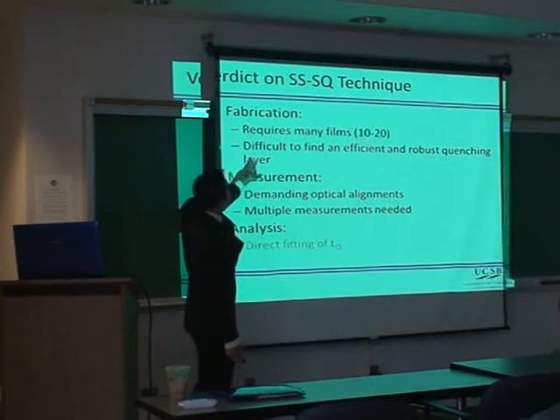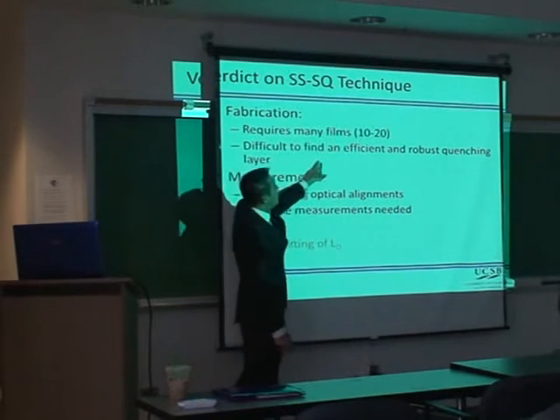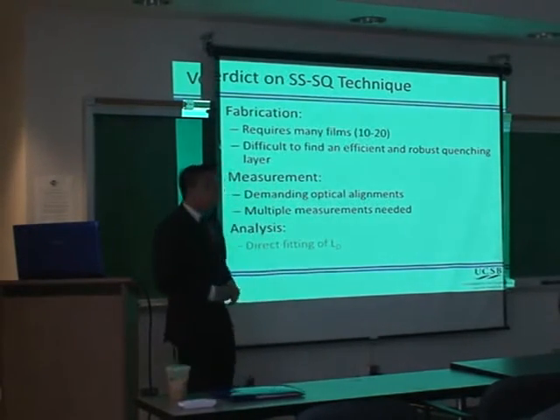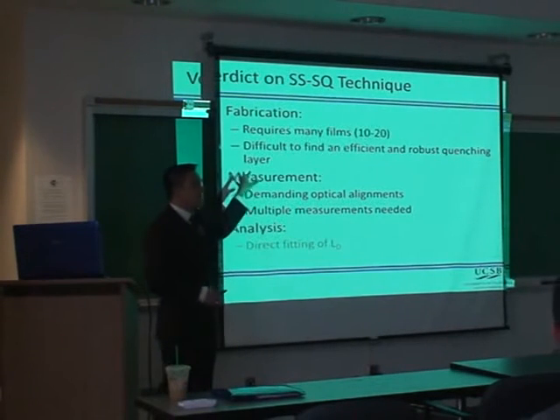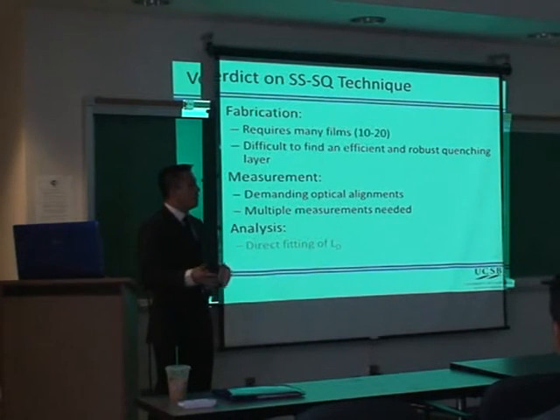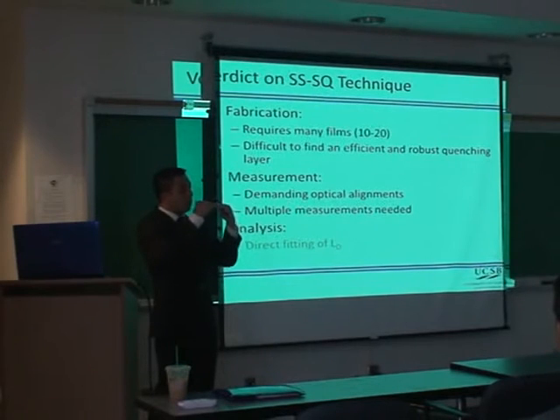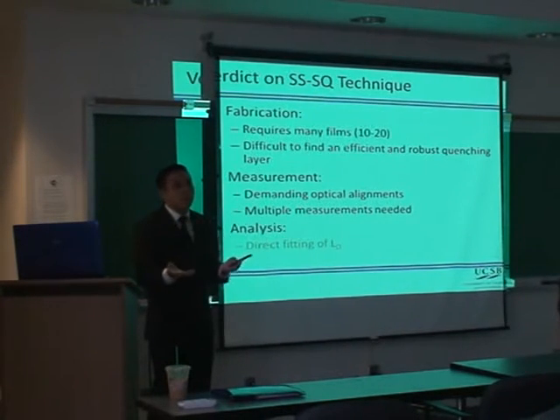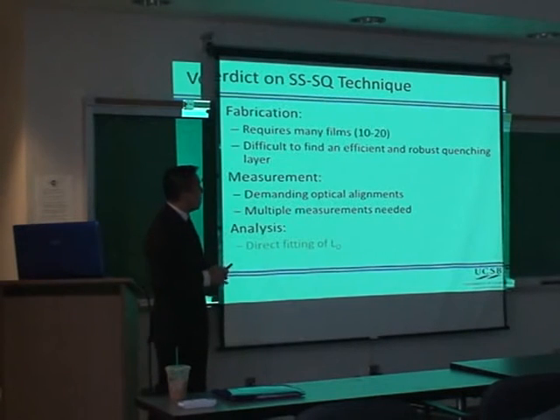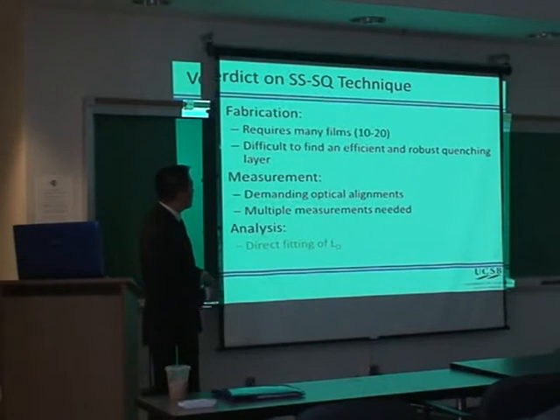In addition, I didn't discuss, but it's actually very difficult to find an efficient and robust quencher. So before using C60, I actually tried a lot of other materials because I wanted to have an interface that was firm, strong, and efficiently quenching. But a lot of materials like TiO2 and polymer acceptors, they just didn't work as well as C60. So finally, I settled upon C60.